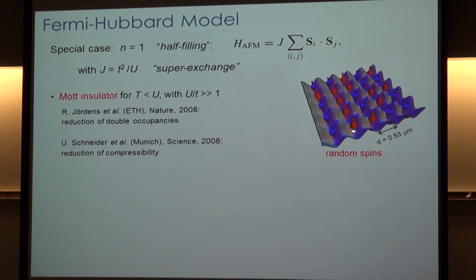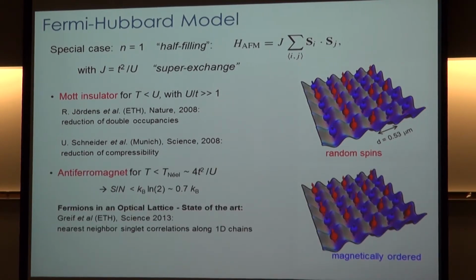Now in that case, you can see over here on this two-dimensional representation of the system that you have exactly 1 atom per site, and the spins are randomly oriented. So in order to see the antiferromagnetism, you have to get to even lower temperatures, which are much lower than this scale where you can see the Mott insulator. The Mott insulator in ultracold atoms has been mapped out very beautifully in experiments, both at ETH in Tilman Esslinger's group, and by Immanuel Bloch's group in Munich. About 5-6 years ago, they actually saw this Mott insulating phase in an ultracold gas of fermions in an optical lattice.